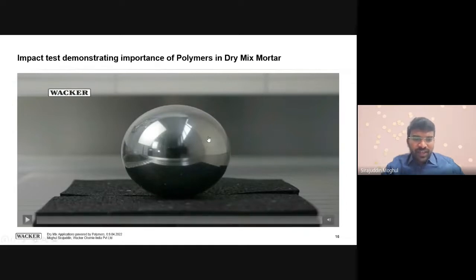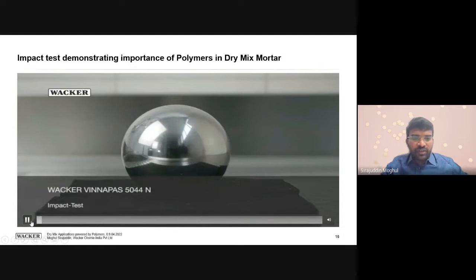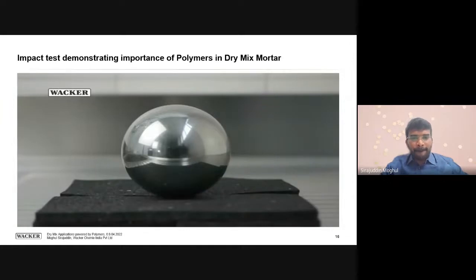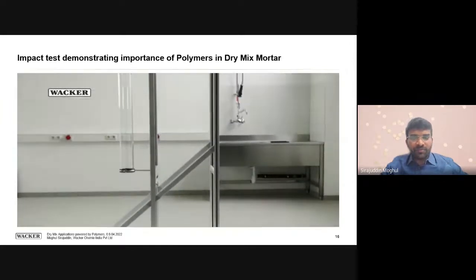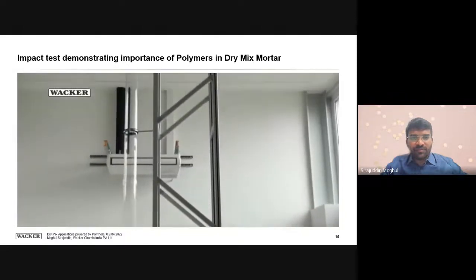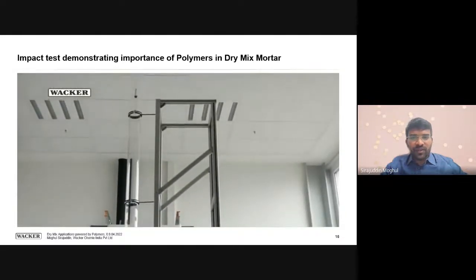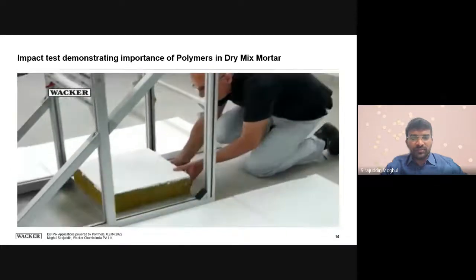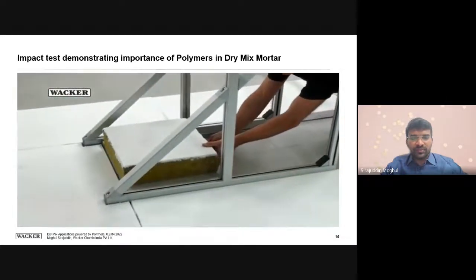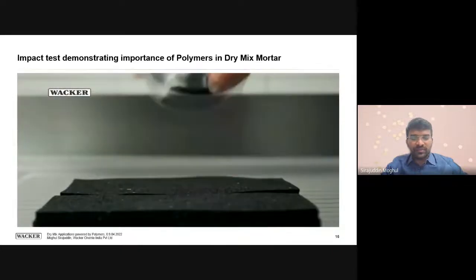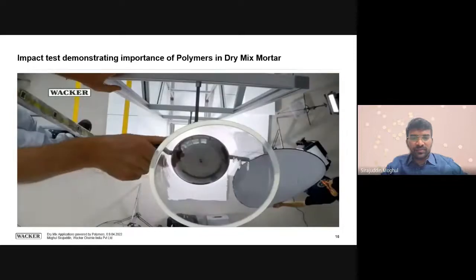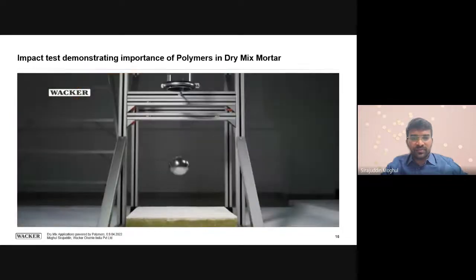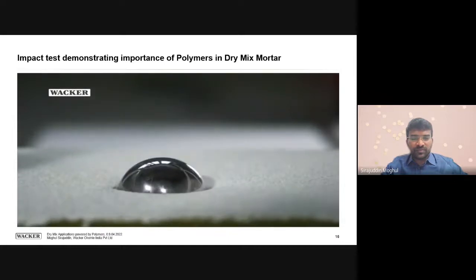See, I would like to end my presentation with this video. The following film shows an impact test on an external thermal insulation composite system. A 3-kilogram steel ball falls from a height of 3.85 meters onto a test specimen, yielding an impact energy of 110 joules. The base coat mortar of the specimen was made with VINNAPAS 5044N polymer powder. Before testing the sample, we dropped the ball, by way of comparison, onto a conventional external thermal insulation composite system comprising a mineral wool board with a simple base coat mortar and a conventional mineral finish coat.